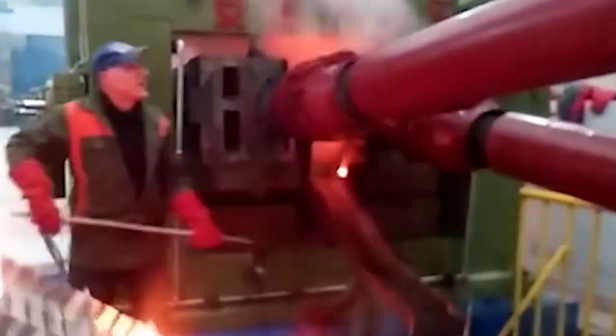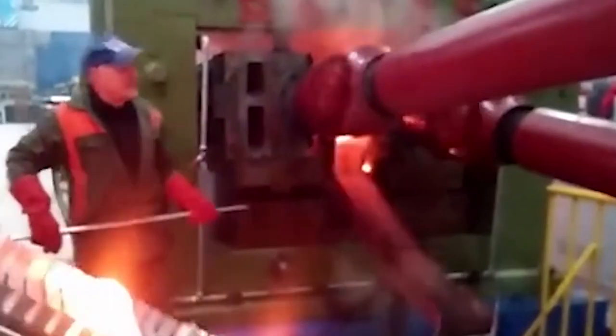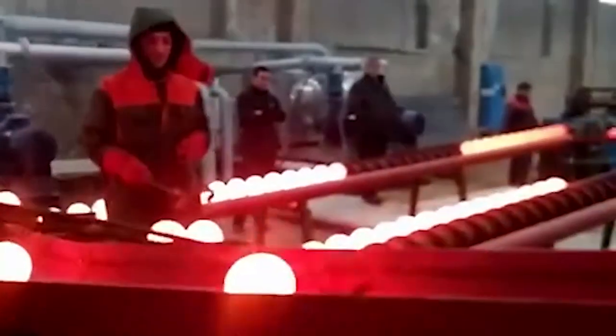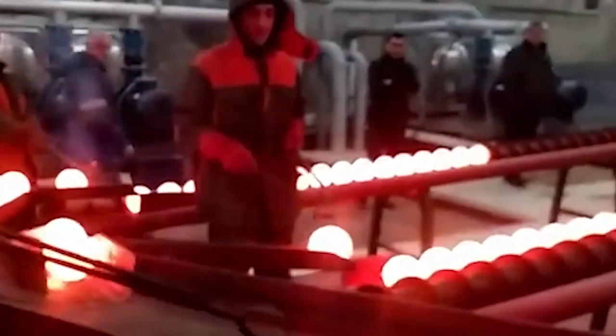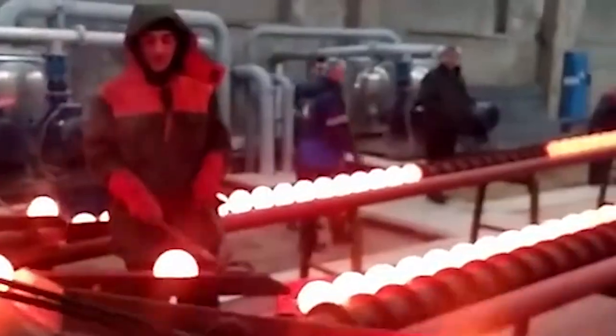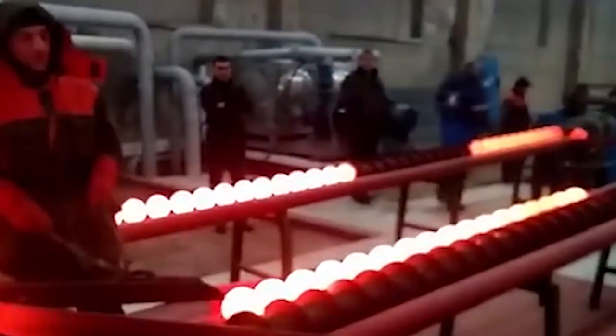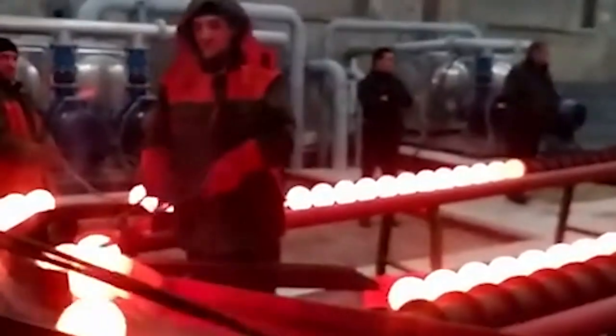Using high sulfur coke and pig iron, when the original molten iron contains more than 0.1% sulfur, often results in poor spheroidization. The molten iron at the junction with gray cast iron is not separated cleanly, due to a calculation error of the charge. The molten iron in gray cast iron is too much, and the molten iron at the junction is not separated cleanly. As a result, high sulfur, low carbon gray cast iron molten iron is mixed into the nodular cast iron,